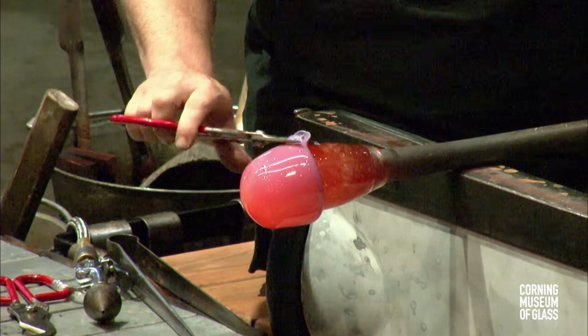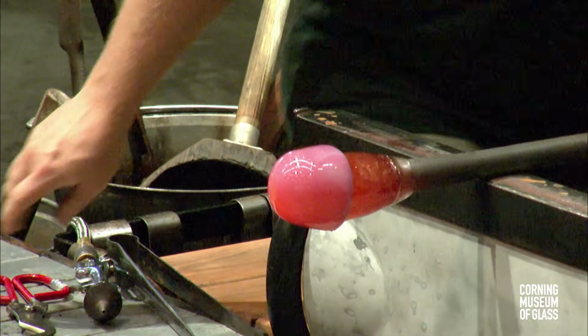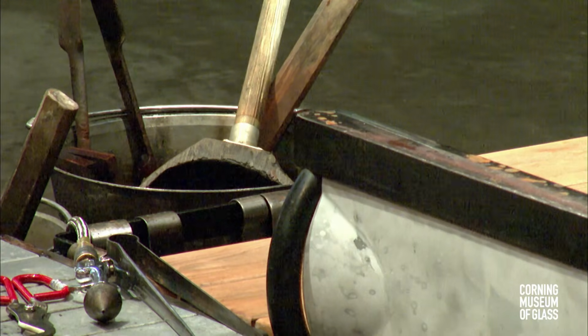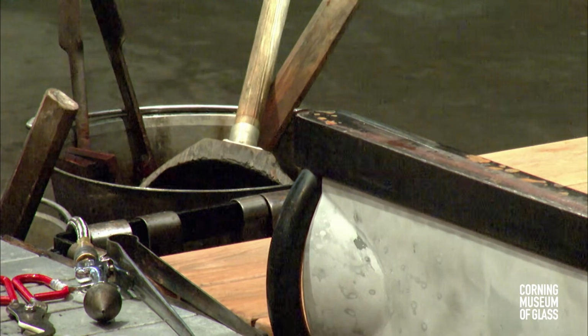Now, unfortunately, when we went to heat this color up, this glass color was heated up in the box over here, because glass, when it heats and cools, it expands and contracts. And so if it heats and cools too quickly, it will end up cracking. So we needed to take that big chunk of purple glass, and we put it into the oven over here, and we warmed it up slowly so that it could be picked up on the end of the iron and heated up. But I guess we didn't go slow enough, because when we picked up that color and we went to introduce it to the hotter reheating chamber, it cracked in a few places.